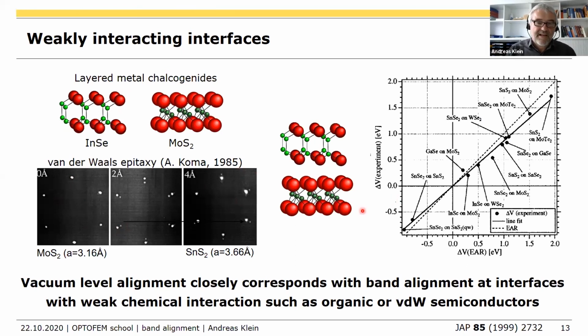And now if you measure experimentally, so this was done by my colleague Rüdiger Schlaf, when I did my PhD, and he did that for many different combinations of layered semiconductors. If you measure the valence band offset and compare it with the valence band offset given by the vacuum level alignment, you see that this follows very nicely. But that's a very rare situation. This is because there's only weak chemical interactions at the interfaces.